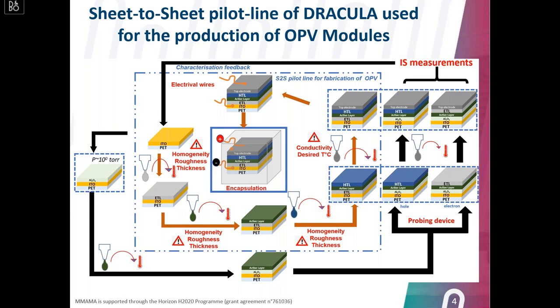For that, at each step, after printing each layer, we should control all these parameters. Especially for some layers, we should control the conductivity, as we need to extract charges and put them in the external circuit, so we have to use some conductive layers. And then we have to measure the conductivity of these different layers. You will see that during this project, we developed, in collaboration with different partners, and validated different methods to help us have all this information to validate our process.